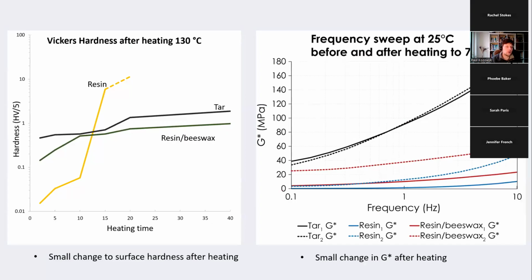To look at the thermal degradation of the material after heating it, the hardness measurements were taken at 5 minute intervals of heating the material. The tar in the black here shows very little change after heating it for up to 40 minutes. The pure resin, on the other hand, changes very quickly with heat. And after just 15 minutes, it becomes so brittle that you can't take the measurement anymore. It just shatters and breaks. The resin in beeswax is a bit closer to tar, but still has a little bit more variation.